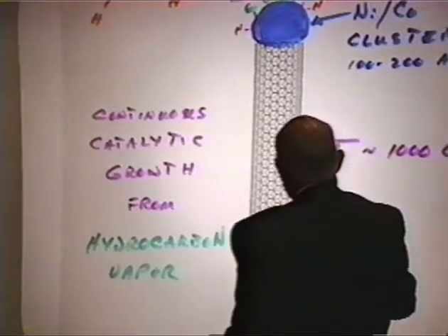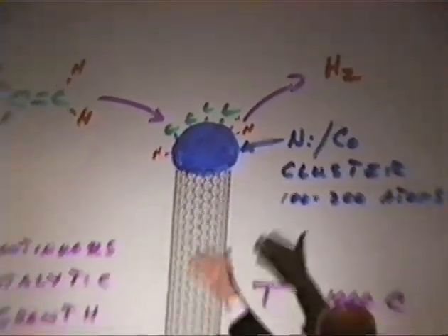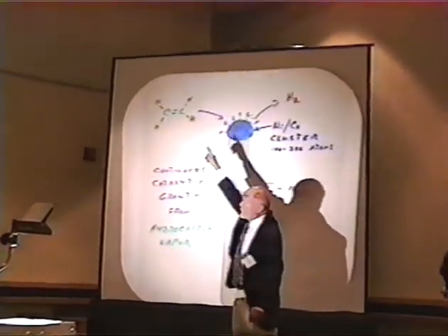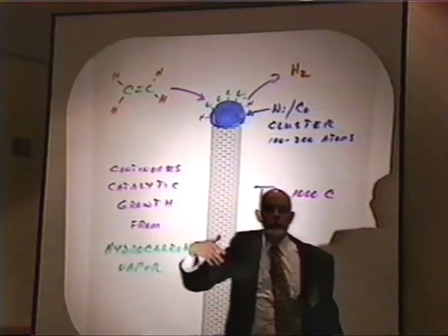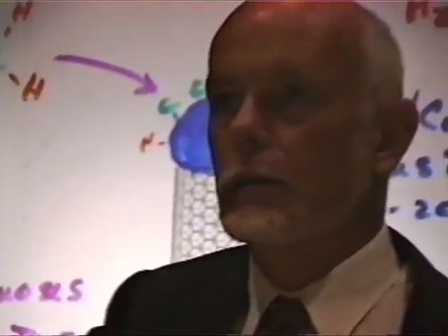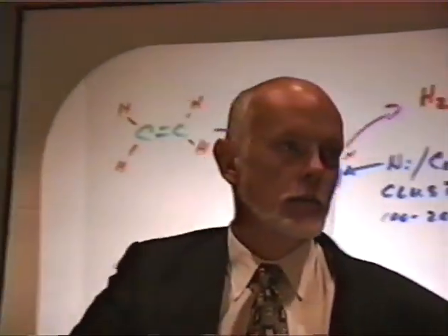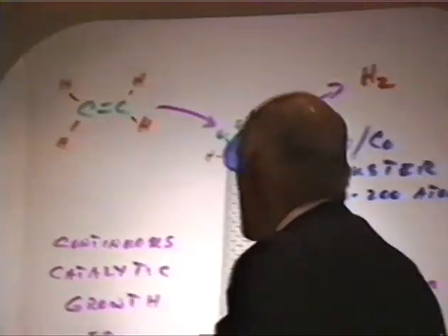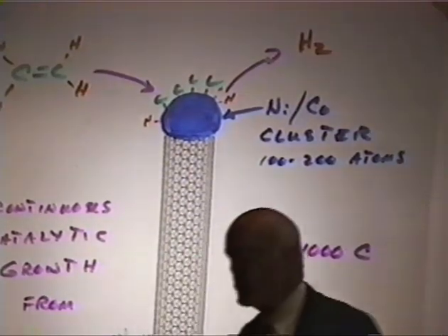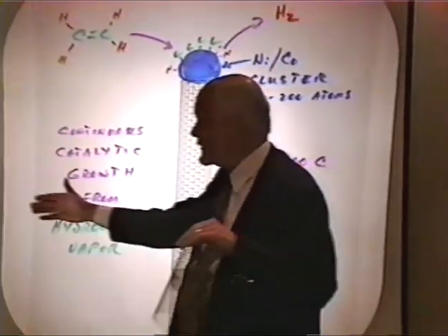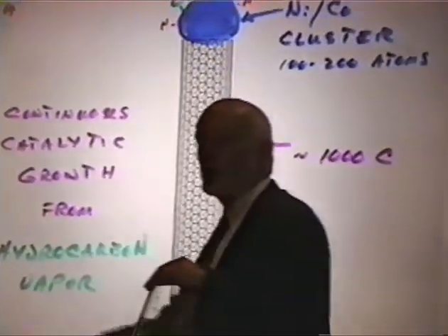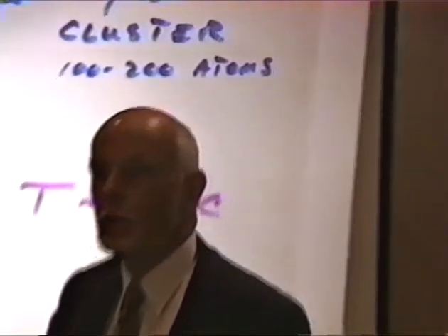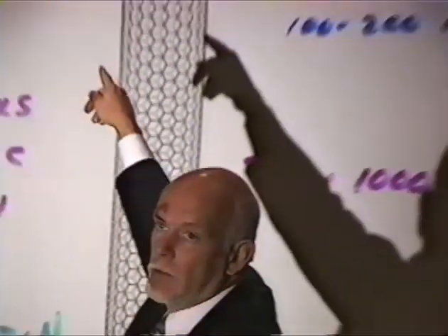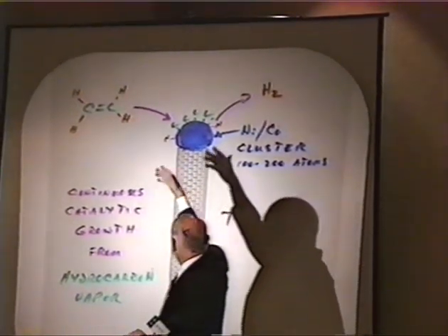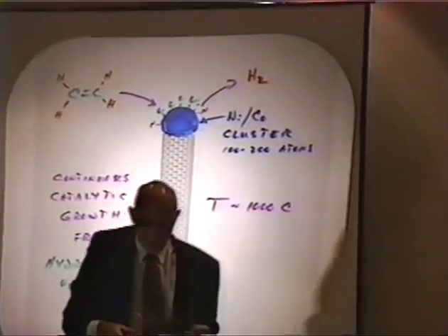It potentially could grow quite rapidly and maintain its perfection, because it's only a nanometer from here to there. One of the difficulties in crystal growth is you have to make sure that there's enough time for bad things to get unbad and the feedstock to diffuse over to some place that can be good. So diffusion is a problem. Well, diffusion has this terrible problem that if you go to longer distances, it takes much longer in time, by the square. But if you turn that problem in reverse, when you get smaller, things get much better and much quicker. 1 nanometer makes diffusion not a problem at all. So this thing has a chance of growing with great perfection at high velocities.